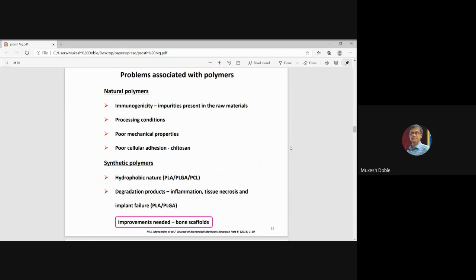Many of them are approved by FDA. PLA, PLGA, PCL, they are approved. Chitosan, natural polymer, is approved by FDA. Silk is approved by FDA. And synthetic polymers, the problem is when it degrades, the degradation products could be causing toxicity issues and inflammatory issues. For example, lactic acid from PLA or acrylic acid from PMMA could be toxic and causing some problems. Implant failure. Okay, the implants after some time can fail. Like I mentioned, the early failure is mostly related to biofilm, and the later failure is related to immunogenicity and biocompatibility issues actually.